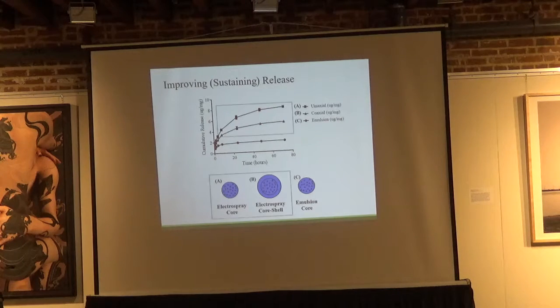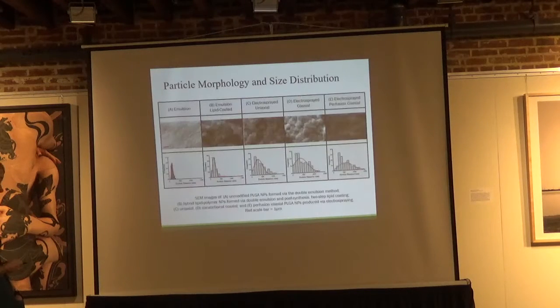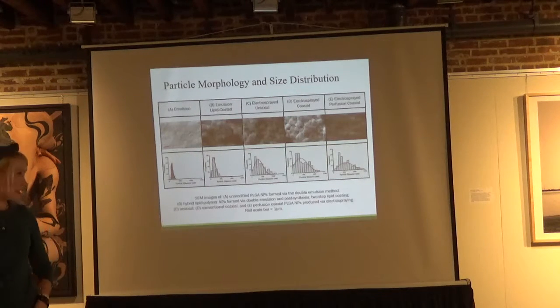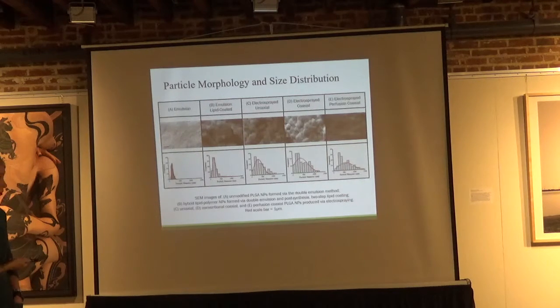And so we initially looked at this and we saw very favorable release from our uniaxial and coaxial groups relative to, again, the pretty poor release that we saw in emulsion-based characteristics. We did a more thorough characterization of this, and one of the drawbacks about using electrospraying is that particle sizes tend toward the more micron size. So where we're at now, and Keegan, he has unfortunately not had time to be in lab this semester, but we're trying to get these particles closer in size by adding a number of ionic agents to our emulsion-based particles that range from about 160 nanometers in general. We're trying to get these other sizes down because of their favorable release characteristics.